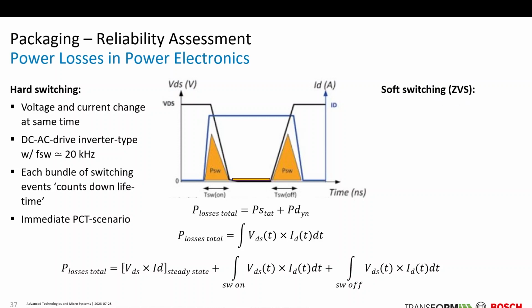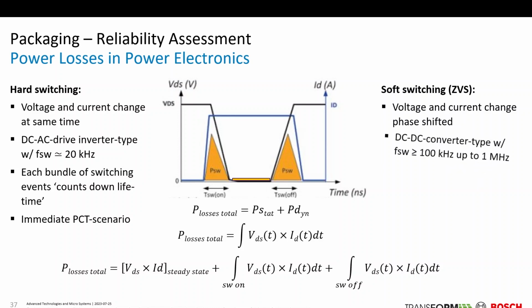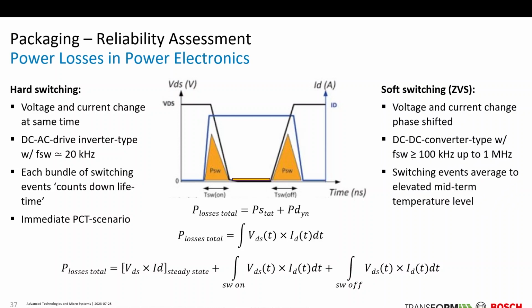But as well, we see the soft switching scenario, very special for DC-DC converters or for charging converters. Then the voltage and current are phase shifted. Okay, this graph is not so valid any longer, but nevertheless the principle is given. This is quite typical for converter types with high frequencies in the switching events, but nevertheless the switching events average to something like an elevated midterm temperature level, and it's more or less related to this TCT scenario. So try to differ. Hard switching means you are in this more or less PCT world. With a soft switching application, you are more or less in this TCT loading scenario then.